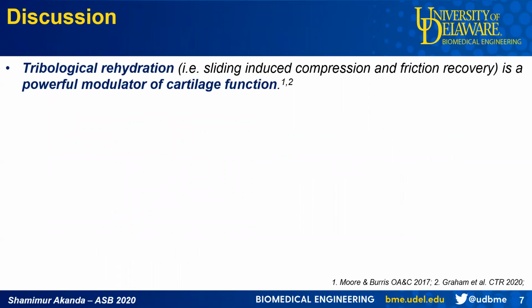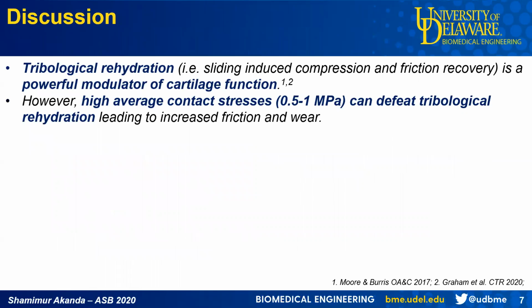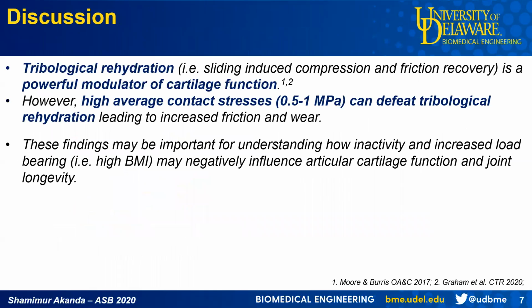So tribological rehydration is a powerful modulator of cartilage function. However, high average contact stress can defeat tribological rehydration, which can lead to increased friction and wear. These findings may be important for understanding how inactivity and increased load bearing may negatively influence cartilage function and joint longevity.